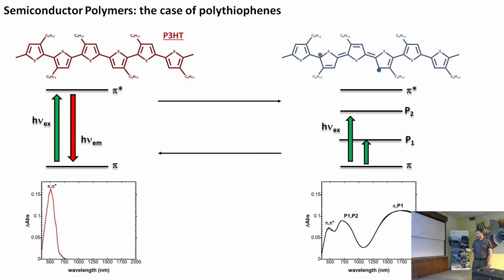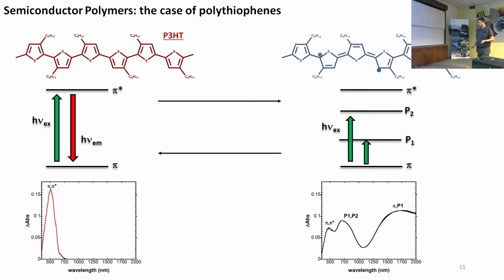If you have the polymer in a neutral form, then you have the conjugation of each monomer that will lead to what we can call a pi-pi star electronic transition. And so you get this neat electronic transition that will give the color of this polymer. If you oxidize, however, the localized excitation or the exciton is going to be electrostatically attracted by the positive charge, and so this level of energy decreases and produces two different levels of energies that we are going to call polarons. Polaron 1 and polaron 2.